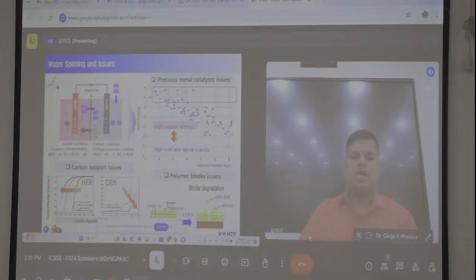When they use it for the HER, you can see the potential loss after a few cycles. Usually a lower potential is very good, but with the potential loss after a few cycles, we cannot use the catalyst for long-term usage in industry. In the case of the OER it is similar. When used for the long term, the potential may shift towards the positive, and there is the same issue for iridium or ruthenium based oxides.